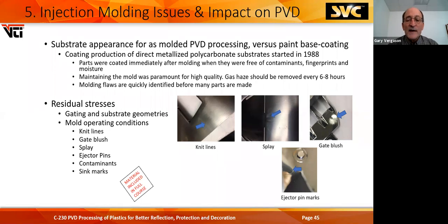Parts that are coated immediately after molding are free of most contaminants and moisture. You've got to maintain the quality of the mold, and molding flaws are quickly identified. We'll get into much more detail in the full course, but here you can see a knit line, where the material comes around and you have a cold joint. And unless you're paint base coating that, and even if you are paint base coating it, you'll still see it.